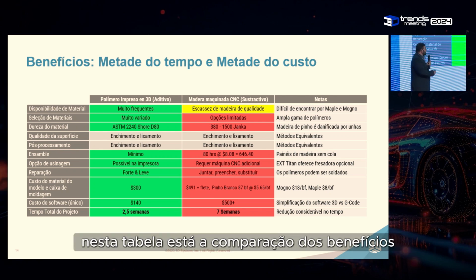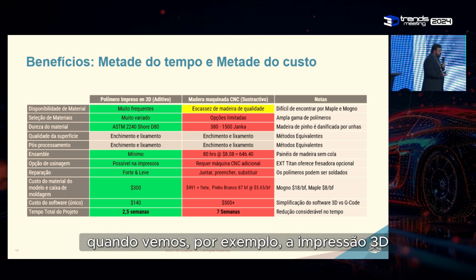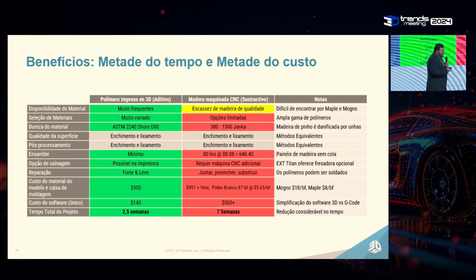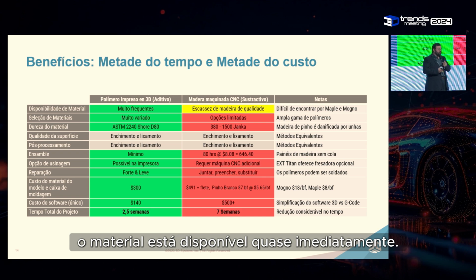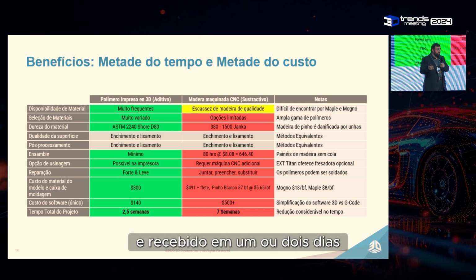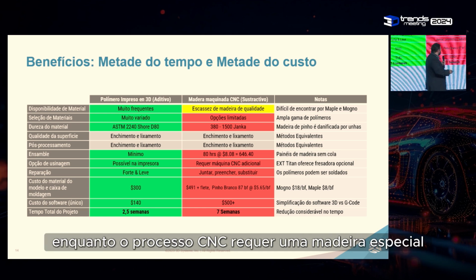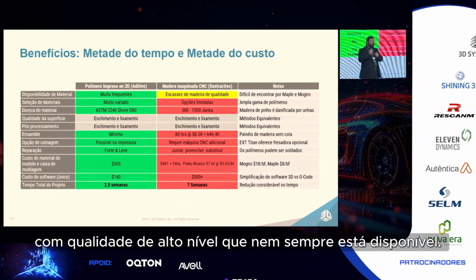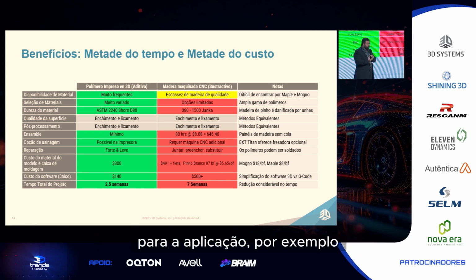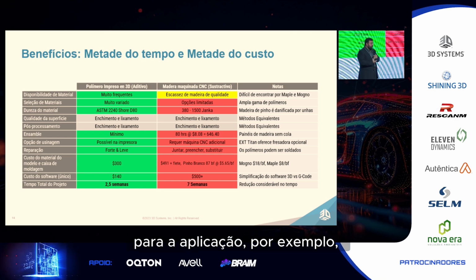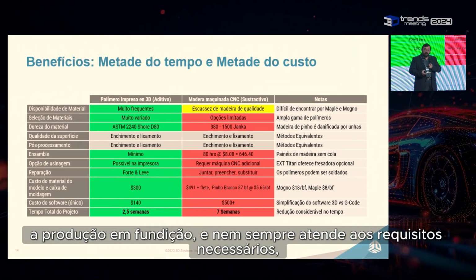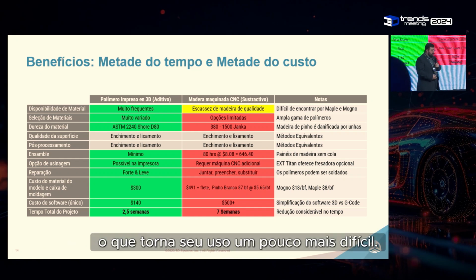Here, for example, in this table is the comparison of benefits for 3D printing. The material is available almost immediately. Those are materials in stock that can be ordered and received in 1 or 2 days, while the CNC process requires a special wood with high-grade quality that is not always available. Another limitation is that even if the wood is available, it needs to be under certain parameters for the application. For example, the same wood used for furniture is not the same as for production in a foundry, and it does not necessarily always meet the requirements, which makes it a little more difficult to use.